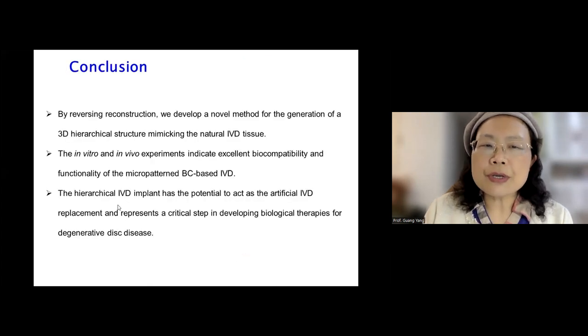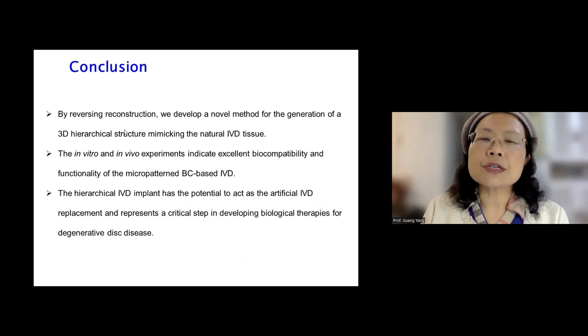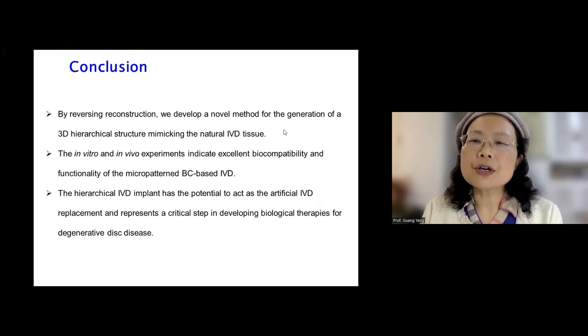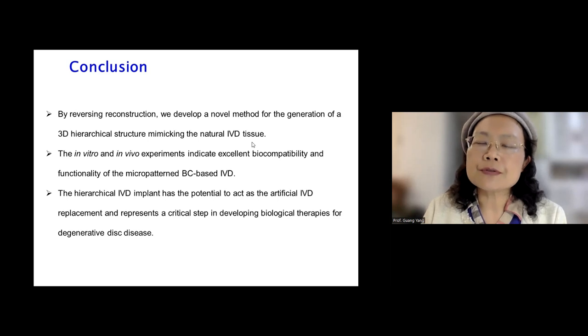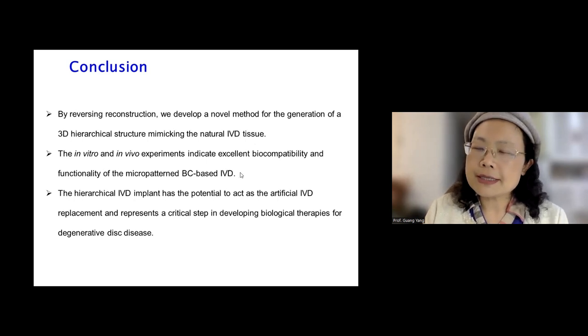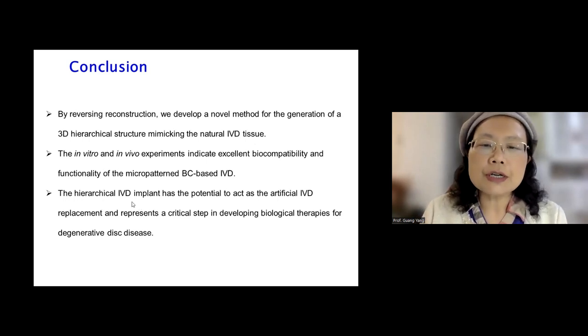Based on that, we used this reverse reconstruction of the structure, and we developed a novel method for generating the 3D hierarchical structure mimicking native IVD tissue. And in vitro and in vivo experiments indicated excellent biocompatibility and functionality of the micro-patterned BC-based IVD. The implanted hierarchical IVD has the potential to act as an artificial IVD replacement and represents a critical step in developing biological therapies for degenerated disc disorders.